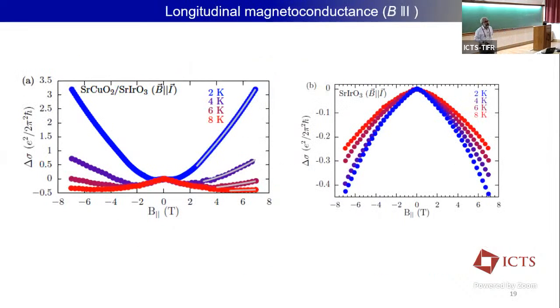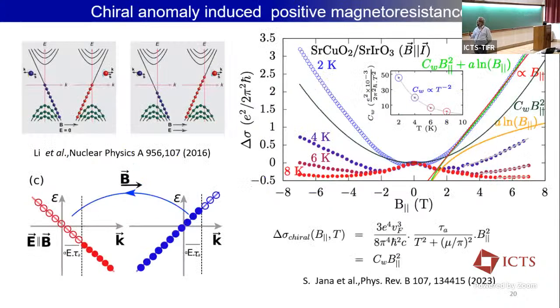Then we looked into the longitudinal magnetoconductance, and here we see a sharp difference. When you see this bilayer, we see a positive magnetoconductance, and of course this is measured with B parallel to I because we are looking at the chiral anomaly. But for only SrIrO3, it is completely in contrast. One is positive, one is negative. So we tried to understand this based on the formalism of the chiral anomaly, generally used in the context of topological materials that show positive magnetoconductance.